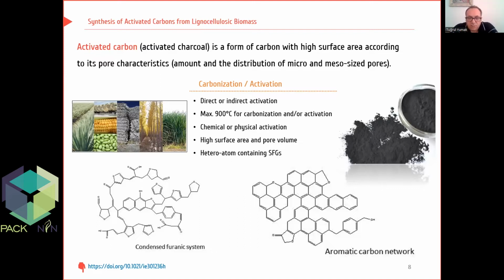The mechanism and the operating temperature of activation depends on the type of activation used. For example, in the case of zinc chloride, the porosity is created by the spaces left by the reactant after washing, while with KOH, the reagent starts the activation process at higher temperature, above 700 C.